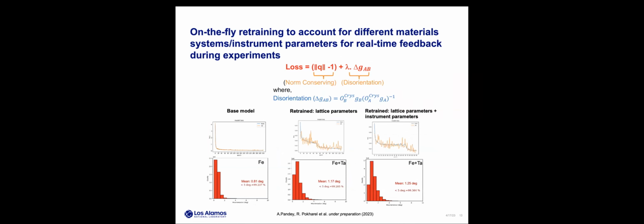And the map here in the middle shows the deviation of the quaternion norm from unity. In the absence of ground truth, which we need to know to calculate the misorientation map, you can see that this map shows very similar features as the misorientation map. So in the absence of ground truth, you can use this as a metric to gauge the accuracy of your reconstructions. And one thing to note is that these ML models are instantaneous, and you can reconstruct these full 2D maps pretty much instantaneously. This approach can be extended to various material systems and different instrument parameters.